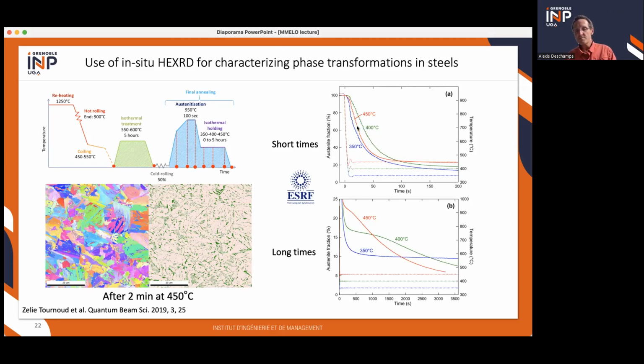So with in situ X-ray diffraction at high energy, you can get a very good time resolution and follow the phase transformations if you have good diffraction conditions and small grain size and so on. We can discuss later on during the discussion the experimental conditions that need to be fulfilled. Anyway, at short times, you can see that the transformation is very fast. It's not too much temperature dependent. And if you go to longer times, the situation becomes more interesting.